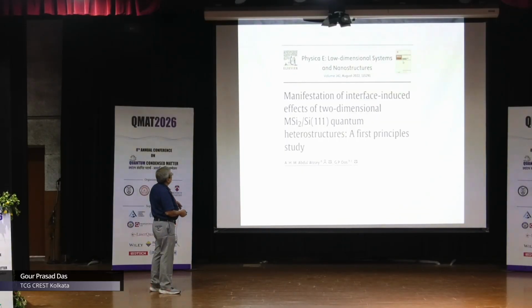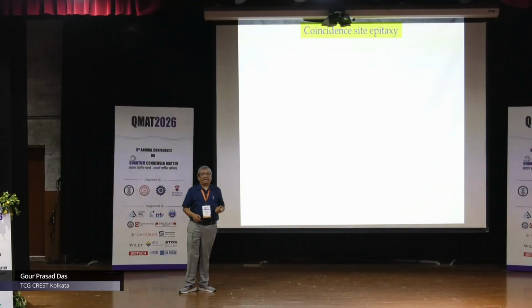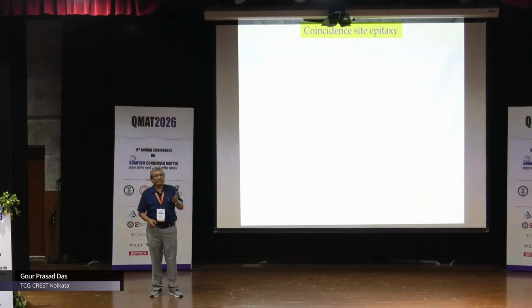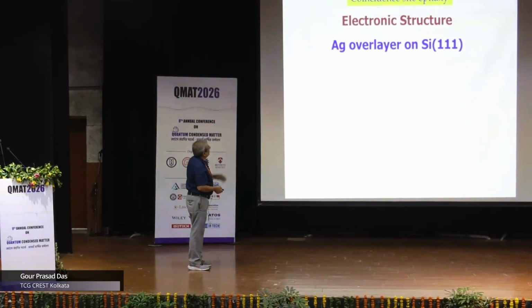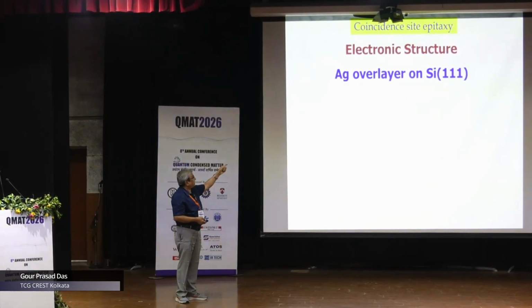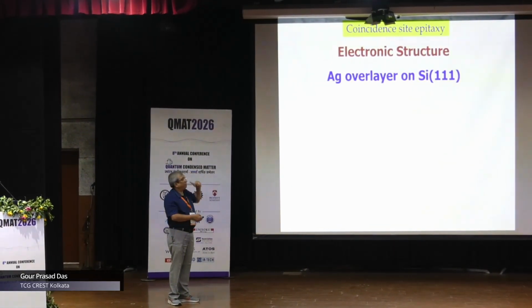Much later we worked on similar systems, but using what is known as coincidence site epitaxy. Now, this is again, the experimentalists know coincidence site epitaxy means it is not lattice matched, it is lattice mismatched. But then what do you do? In a lattice mismatched interface, at the interface you force the metal to have the same lattice parameter as that of the substrate, but adjust it when you go along the Z direction. And this is something which we did for silver overlayer on silicon 111. Remember that silver and silicon don't lattice match, unlike the previous example.